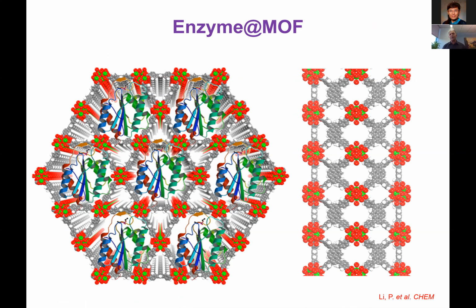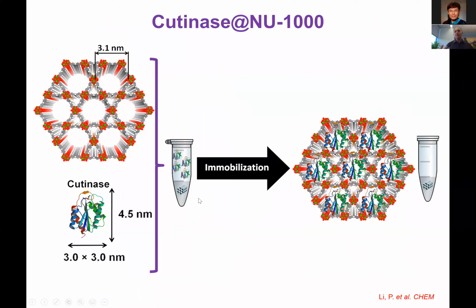How can I convince you that the enzyme is in the hexagon only and not the triangle? And how do we do the synthesis? It is really after we make the MOF and we make sure that we are under the right conditions. We know the zeta potential of our MOF. We know the zeta potential and the surface charges of the enzymes. And under the right conditions, we could immobilize these materials.